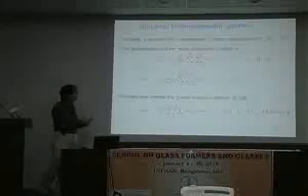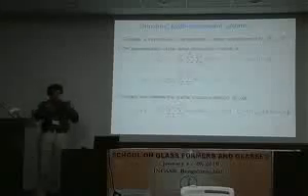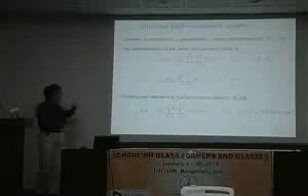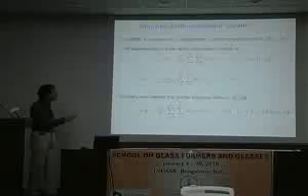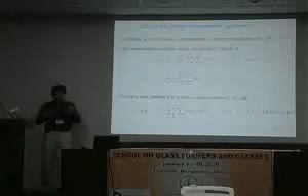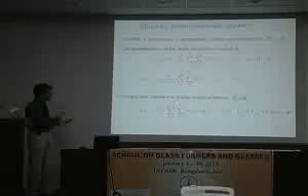Okay, and so what you can do now is to generalize the radial distribution function by considering pairs of a certain type. So let's say if you have particles of type 1, 2, and 3, you can look only at pairs between particles of type 1 and type 1, and you take the thermal average of these distances, and you get this partial radial distribution function G alpha alpha, where alpha runs from 1 to nu. But then you also can look at the particles of type 1 and see where are the particles of type 2, and you look at the statistics of these distances. So this is the G alpha beta.